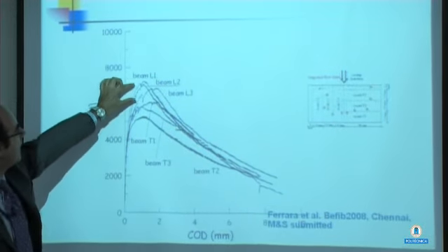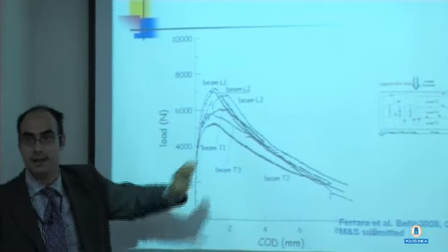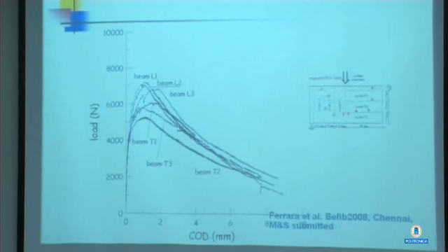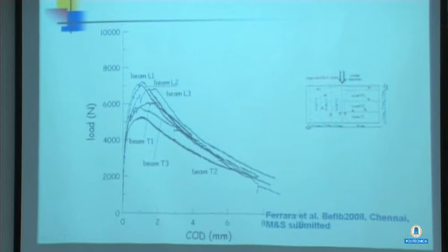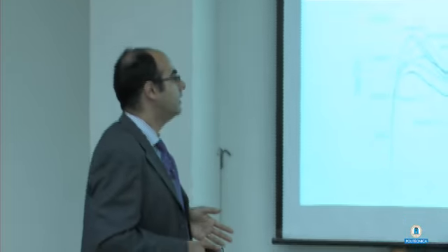These are the results when you cast in the radial direction. You still have some difference. These were parallel to the casting, these were transverse to the casting. There is still some difference, but not as huge as in that direction, probably because in this case the orientation is more random, less preferential like in the case before.